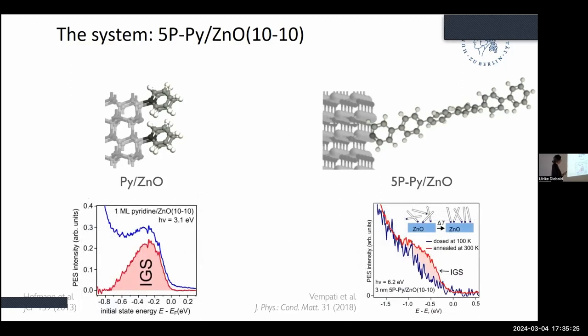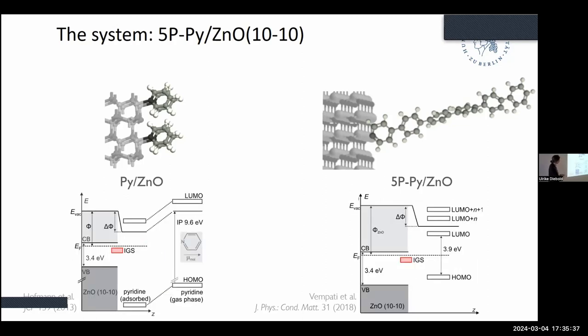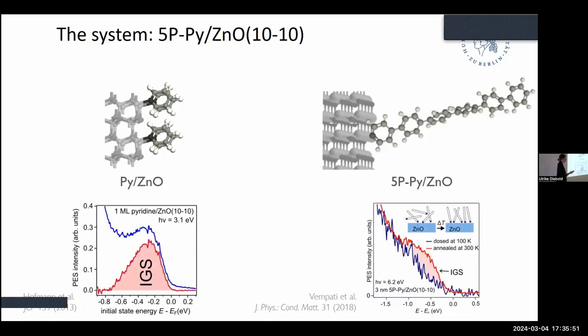And then one other aspect is in common for both interfaces. In both cases, we observe an in-gap state just below the Fermi energy here and there. It's in the interface region, and it must be somehow connected to the pyridine binding. Unfortunately, theory doesn't find it, but it's there.